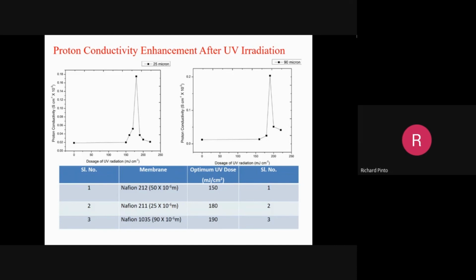And see the effect you can see here, proton conductivity enhancement at almost the same level. Depends upon the thickness, of course. And this plot depends upon the thickness. The reason for that is there is a particular penetration depth of UV. A thin membrane requires lesser power, lesser exposure, lesser UV dosage than a thicker membrane. So where are the plots here? And it's shown here. Optimum UV dosage is 150, 180.